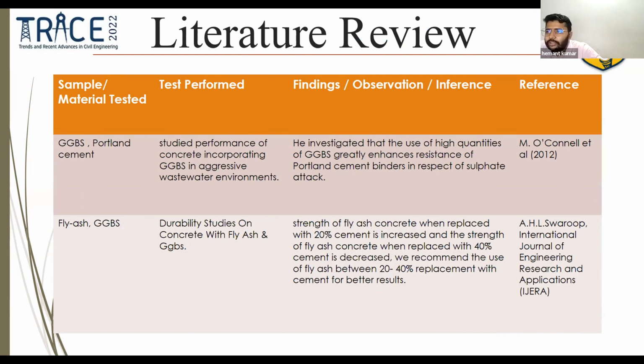Reference: M. O'Connell. Sample material tested: fly ash, GGBS. Durability study on concrete with fly ash and GGBS. Findings: strength of fly ash cement concrete when replaced with 20% is increased, and the strength of fly ash concrete when replaced with 40% cement is decreased. We recommend the use of fly ash between 20 to 40% replacement of cement for better results. Reference: A.H.L. Swaroop.